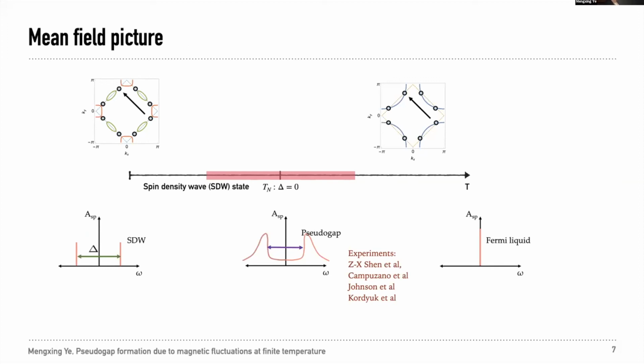However, this simple mean field picture is not what was observed in the experiments. Instead, near the Néel temperature, we see a finite energy maximum, namely the pseudogap, even though the SDW order vanishes. And this is the feature we want to understand.